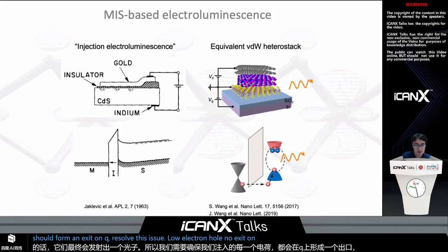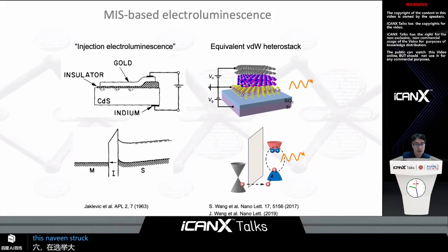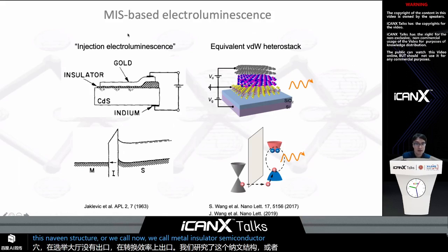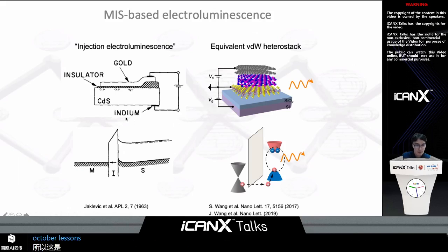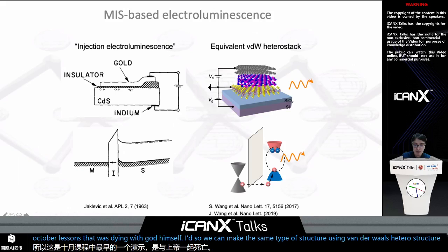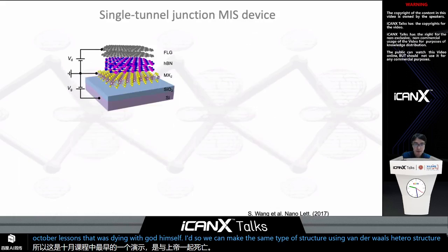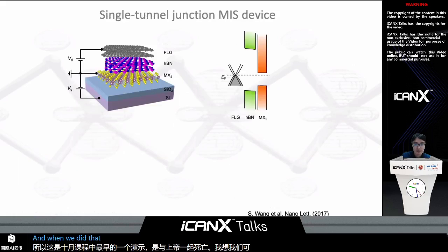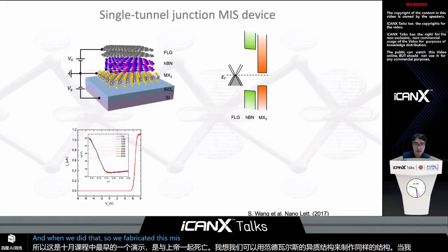Now, to resolve this issue of low electron hole to exciton conversion efficiency, we looked into this device structure, what we call a metal insulator semiconductor structure. This is one of the earliest demonstrations of electroluminescence that was done with cadmium sulfide. So we can make the same type of structure using van der Waals heterostructures. And when we did that, we fabricated this MIS heterostructure.